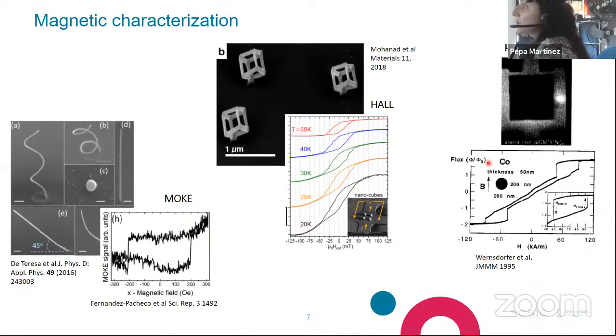And finally, I wanted to show you these measurements. These are also really nice measurements performed in the mid-90s by Wernsdorfer, who was the person who really pioneered this field of nanoSQUID or microSQUID magnetometry. This is a typical hysteresis curve of a particle where a vortex state is stabilized and annihilated. It corresponds to this tiny cobalt particle of just a few 100 nanometers in diameter.